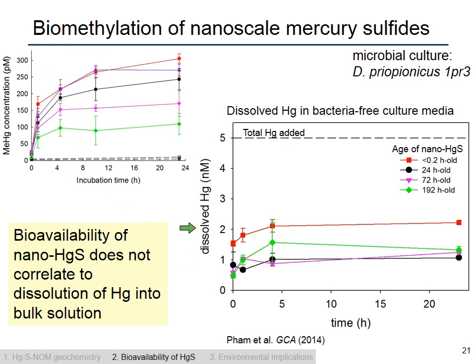This is just dissolved mercury that was quantified when one of these forms of nanoscale mercury sulfide was added to culture media that didn't have any bacteria. So we don't have methylmercury being produced here. And what you can see is that the youngest particle in the red dots, that's less than 0.2 hours old, has a greater amount of dissolved mercury over time. But when you compare the other time points from 1 day, 24 hours, to 192 hours, we don't see much difference between dissolved mercury, even though there's a difference in the methylation potential for these. And the dissolved mercury here, I forgot to mention, was quantified by ultracentrifugation.